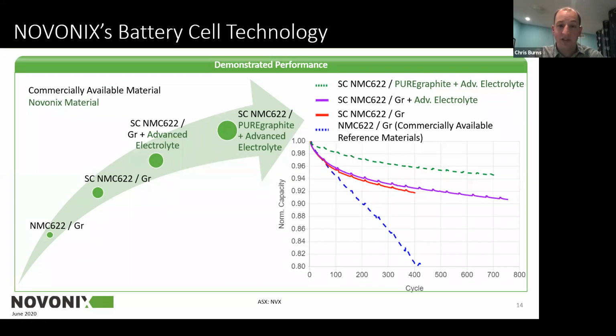And when you look at what this means in real data, you see the NMC graphite with commercial materials in these cell designs and test conditions, about 400 cycles as we saw before. You switch out to the single crystal material, you're at about 92% in 400 cycles. You include an advanced electrolyte package. Again, you can bump that up by 1% or 2%, and you can see that extends out 100 cycles to the same capacity retention. And furthermore, when you switch out the graphite for our pure graphite material, and this is really why people are so interested in our pure graphite material, you get this huge capacity bump in retention relative to traditional materials.